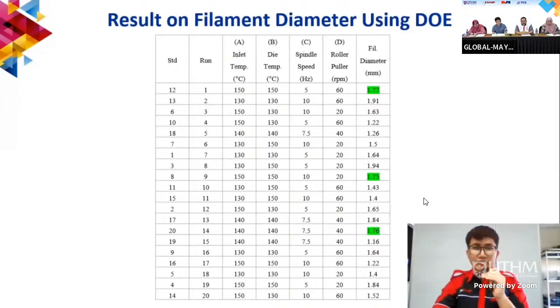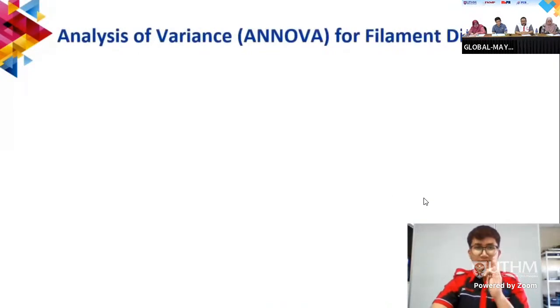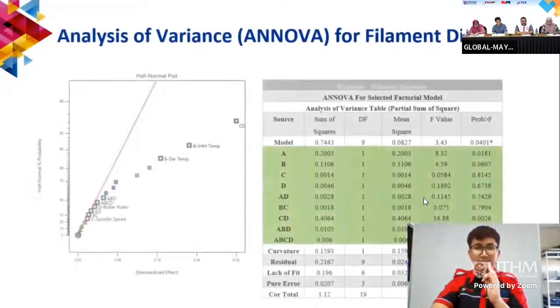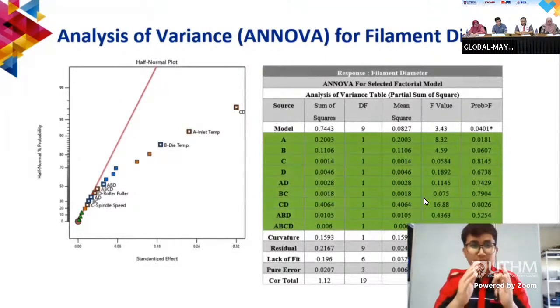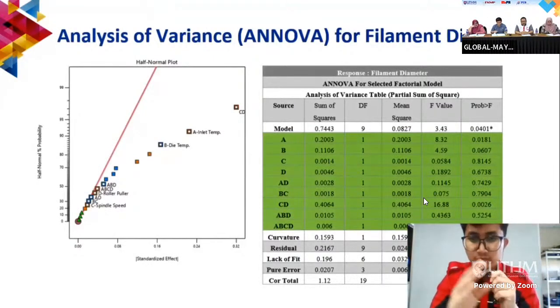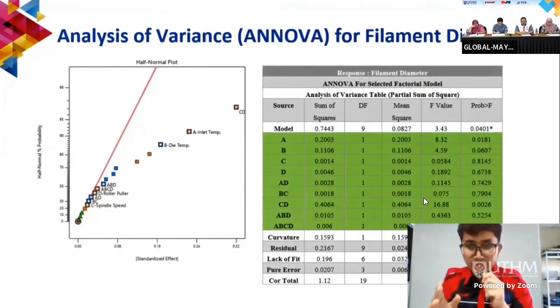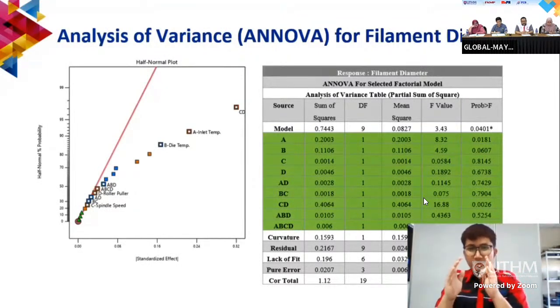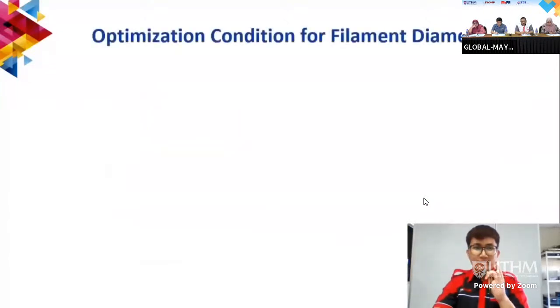From this output, we analyze using ANOVA for filament diameter. With this ANOVA, we get the half normal plot, and then we select the points that have interactions between parameters. From the interaction, we got significant data such as the sum of squares, mean square, F value, and others. From those values, we can get the optimization condition for filament diameter.